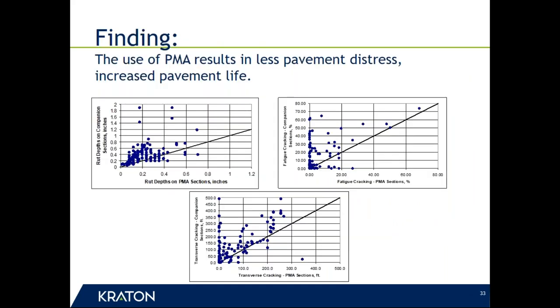The findings on this, if you look at these dots, each dot represents a pair of test sections. And so on the one on the upper left, and let's just pick this one right here. On that pair of test sections, the rut depth that was measured on the unmodified asphalt binder, and I don't know if you can see the arrow here, is around 1.6 inches. For the modified, on the polymer modified, it was less than half an inch. And what you can see on here, and these are lines of equality for each of these distress, this is fatigue cracking here, this is transverse or thermal cracking here, is that there was clearly a lot more distress on the unmodified asphalt than on the modified asphalt binder.